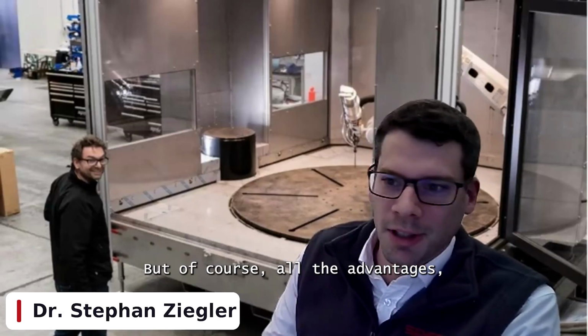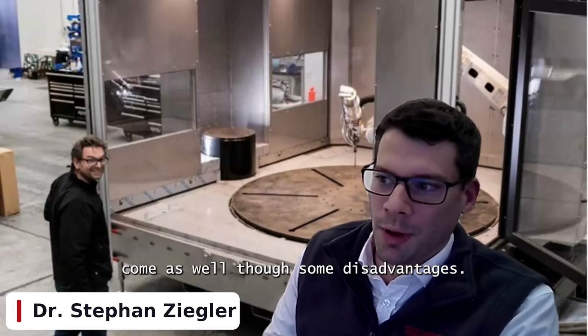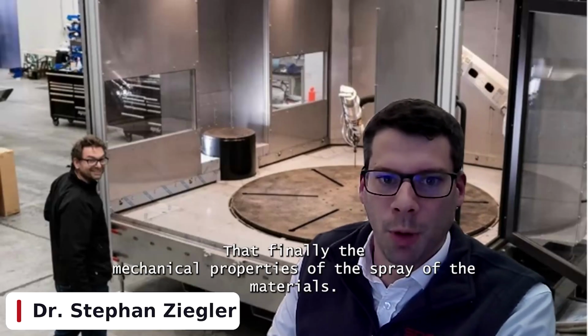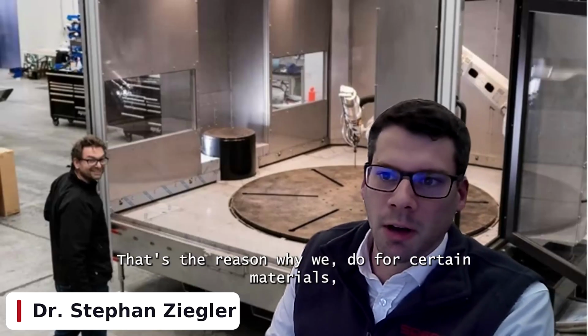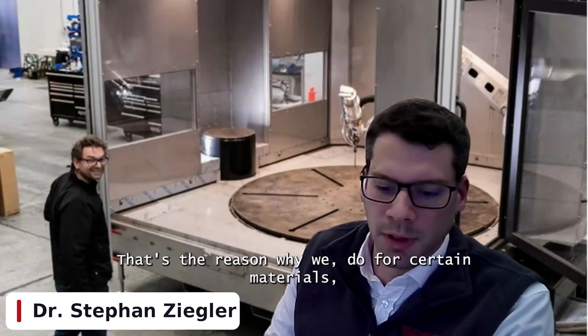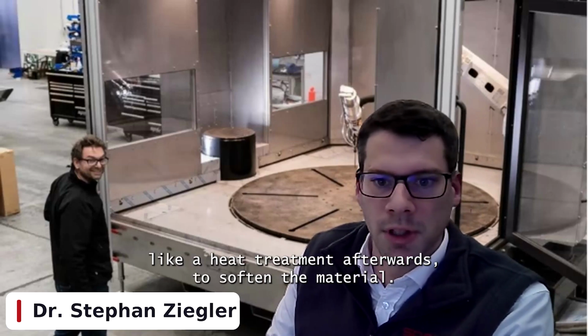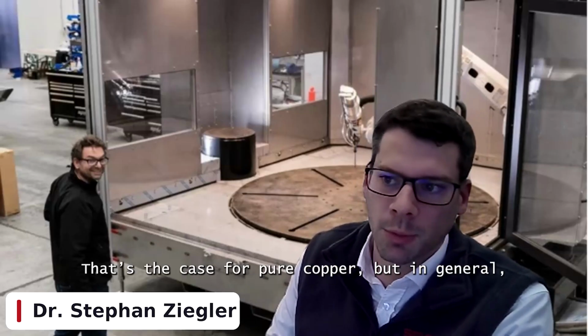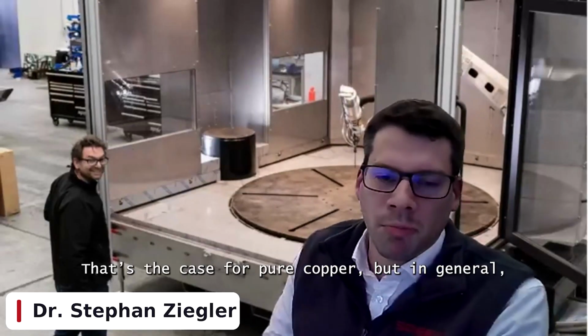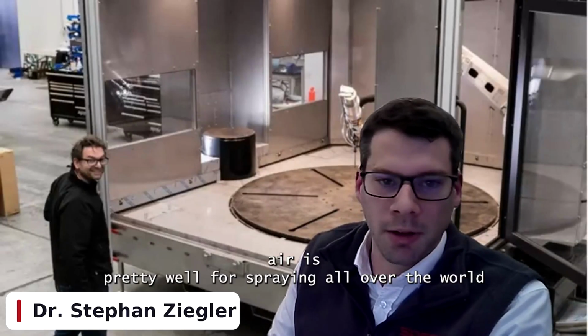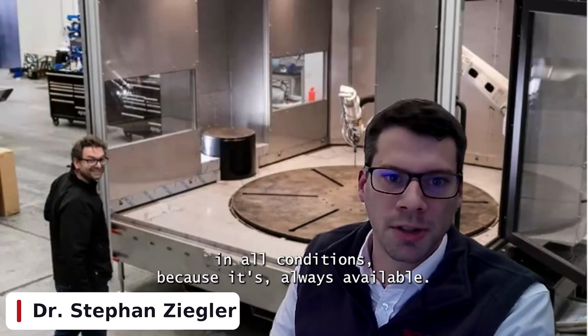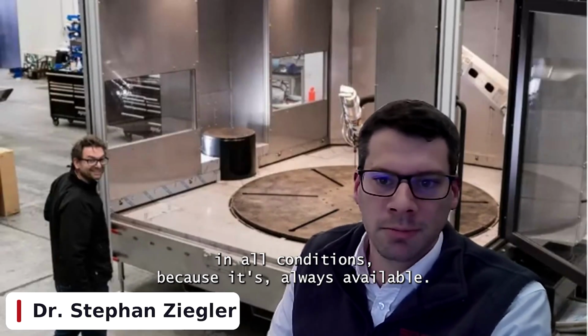But of course, all the advantages come as well with some disadvantages, and that is finally the mechanical properties of the sprayed materials. That's the reason why we do, for example, for certain materials as well, like a heat treatment afterwards to soften the material. That's the case for pure copper. But in general, air is pretty well for spraying all over the world in all conditions because it's always available.